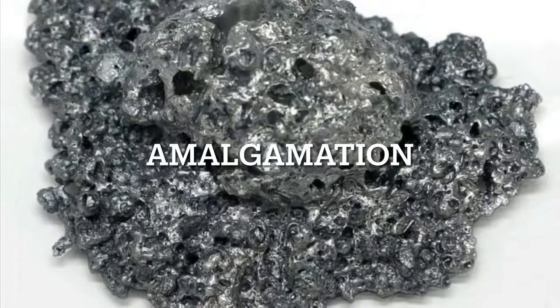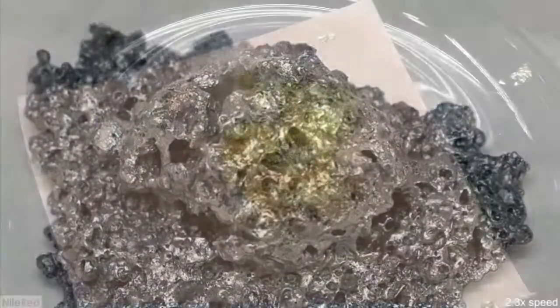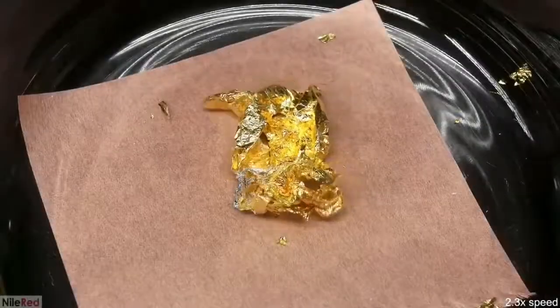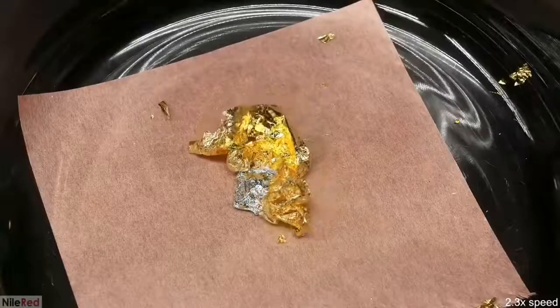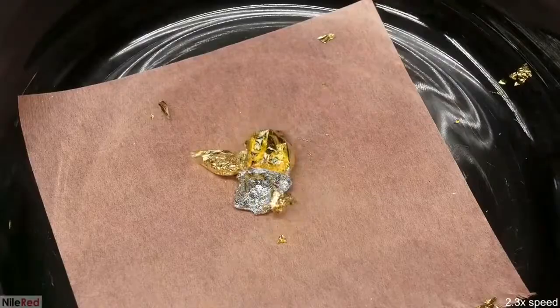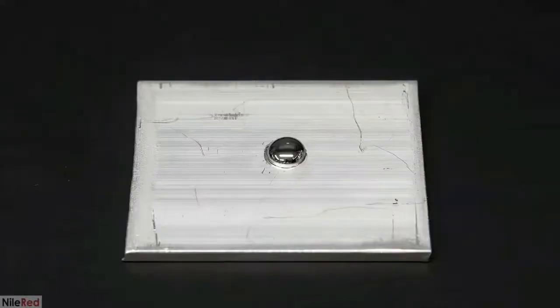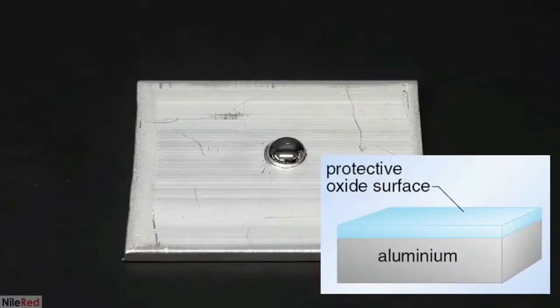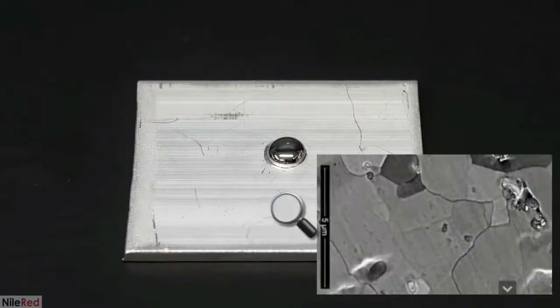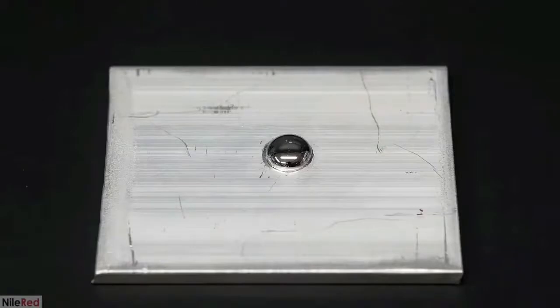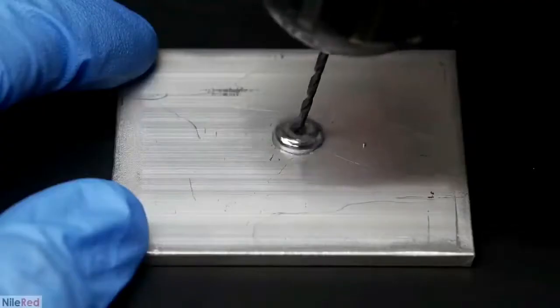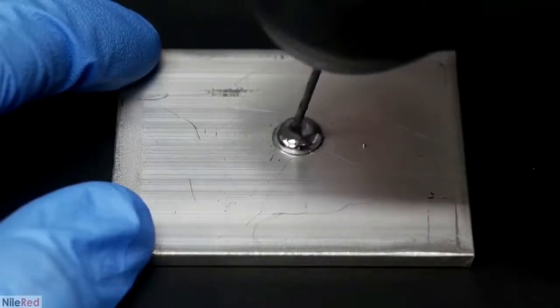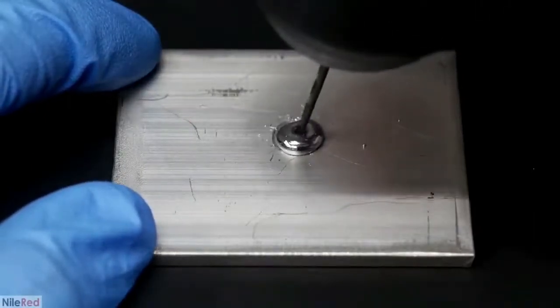Alright, starting with the first mechanism, amalgamation. Amalgamation is a process by which mercury reacts with a susceptible metal, in this case aluminium, to form the metal amalgam. Generally, aluminium is prevented from contacting mercury due to the layer of oxide above it. Even though the oxide of aluminium contains numerous defects, mercury still couldn't penetrate it due to its high surface tension property. Unless there is thermal or mechanical stress or a chemical environment that removes the oxide layer.